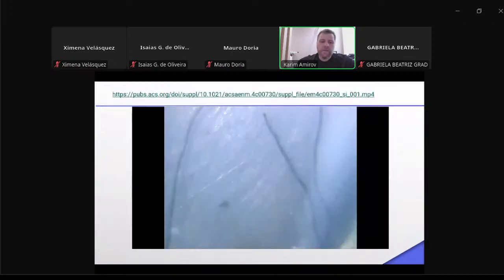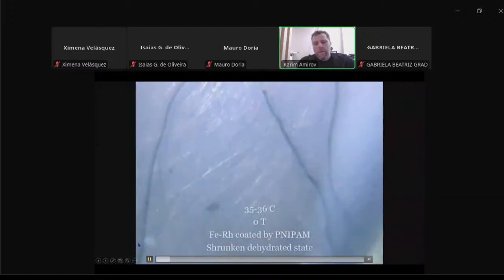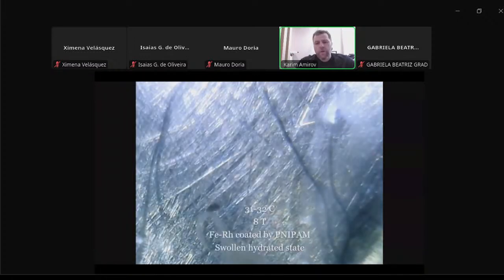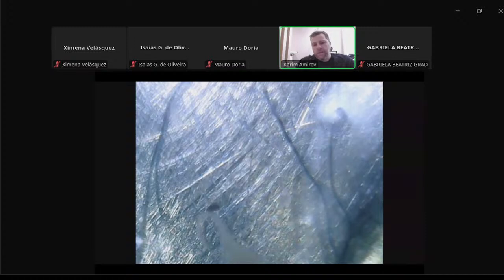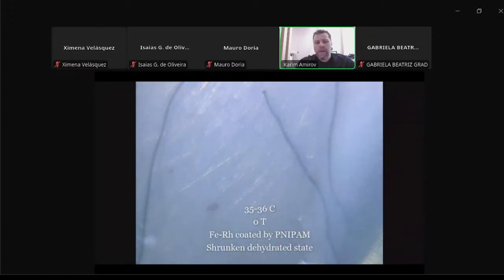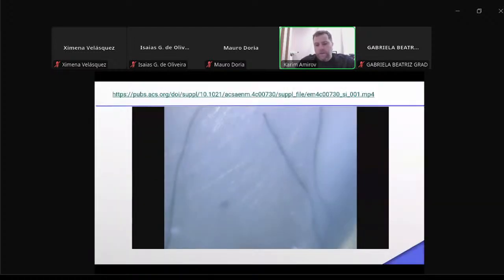And on the next slide, you can see the video. It's a video captured from the camera of our experimental setup. It's with comment. As you can see, you apply magnetic field. It's going to swollen state, and then you remove magnetic field. As you can see, this effect is reversible, and you can both heat and cool down the material. As you can see, the effect works for iron rhodium also.